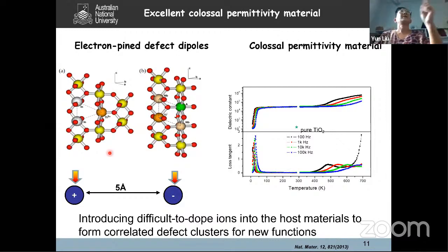Like free electrons, they can hop within these tracks, and as a result we can significantly increase the dielectric constant to over 10,000, whereas the pure one is only 100 to 200. In this case, at low temperature, electrons are frozen. And if you give a little bit of energy to excite these electrons, the electrons will move freely within this defect cluster track.